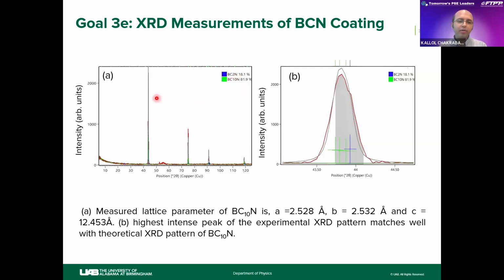If we closely look at our highest peak position, around 44 degrees, the green one is BC10N and the blue one is BC2N. As you can see, it matches very well with the BC10N peak, so our synthesized coating is BC10N. Here is another confirmation.